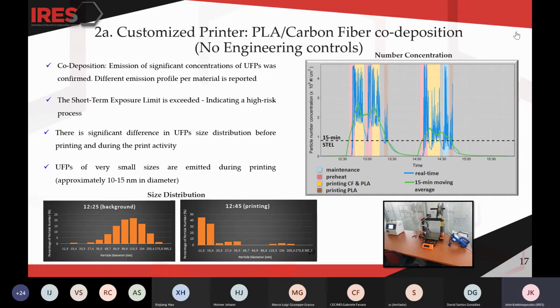Emissions of significant concentrations of ultrafine particles were confirmed. And as we can see from the diagram again, emissions during carbon fibers and PLA printing are higher, with peaks at around 450,000 particles per cubic centimeter, as you can see from the yellow part of the diagram, compared to emissions where only PLA is used, with peaks at around 300,000 particles per cubic centimeter.